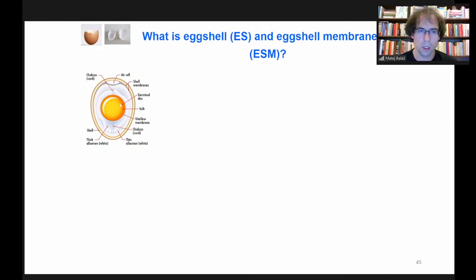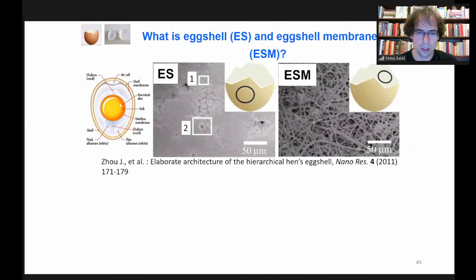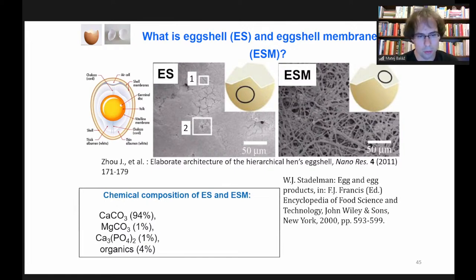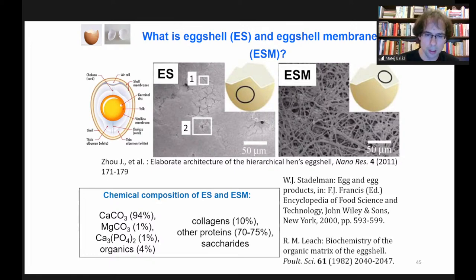When we say eggshell waste, we can say it's a combination of two materials. Here is a nice picture about the morphology. The eggshell is a compact structure of inorganic character with pores, but eggshell membrane is a fibrous structure of organic origin, mostly composed of proteins. If we see the chemical composition of eggshell, we have 94% of calcium carbonate there in the form of calcite and some other inorganic part. And the eggshell membrane, on the other hand, is composed mainly of proteins. We have also collagens in there.